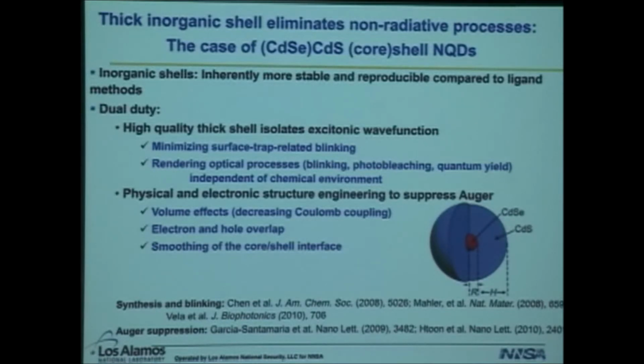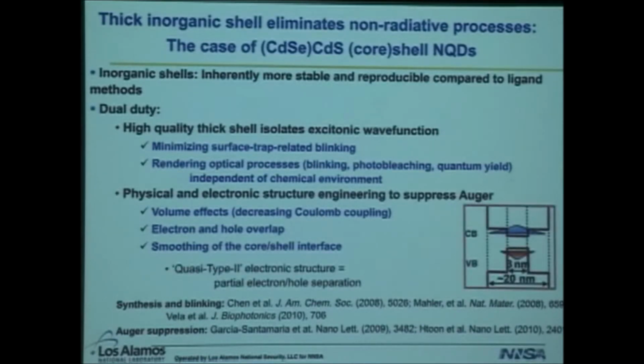Second, if you reduce electron-hole overlap, and that can be done by modifying the electronic structure of a quantum dot heterostructure. For example, what I show here is the case of a so-called quasi-type 2 electronic structure, where we're able to achieve partial electron-hole separation by energetically confining the hole wave function to the core of the quantum dot, whereas the electronic wave function is able to spread out into the shell, because the difference in energy between the conduction band of the core and the conduction band of the shell is relatively small. Therefore you get this partial spatial separation of the two carriers, and that itself can reduce Auger efficiencies.